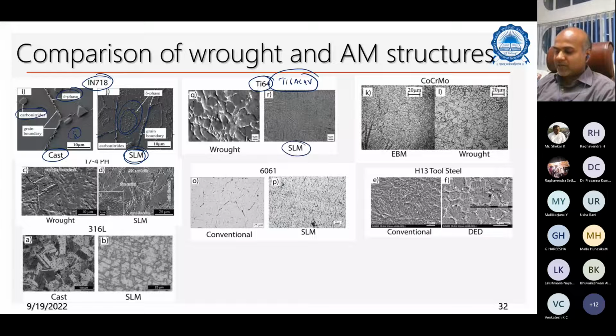Look at the wrought alloys and SLM alloys. What you see in the wrought alloys is proper grains, and there is a certain kind of lamellar structure, which you don't see in the additively manufactured Ti64 alloy, the SLM processed Ti64 alloy. You see very fine distributed phases here. We'll see in subsequent slides, I have much more work to present on this. So what I'm talking about, you see a very fine acicular microstructure here. Okay, SLM process, because of the fast, rapid cooling rates.